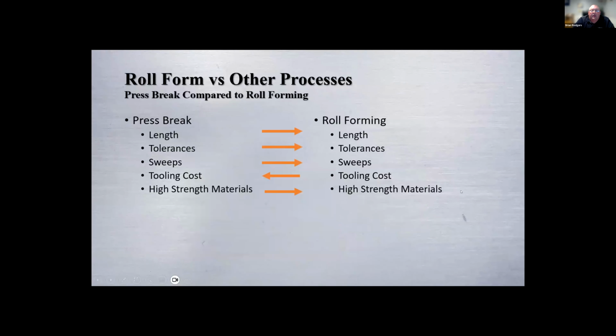So when we look at it, roll forming, like I said, we can run a 400-inch part. We can run an 80-foot part. In a press brake, it's how big is your press bed, right? You have a 30-foot long press brake? More than likely not. Tolerancing, because of the way the press brake process is, you're hitting, pulling out and going back in, roll forming gets tighter tolerances than press brakes.